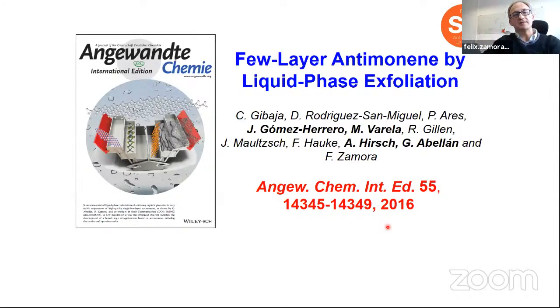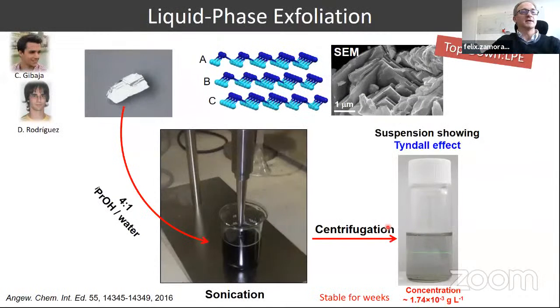And then we decided to extend the possibilities to isolate this material, and we tried to do this isolation by using liquid phase exfoliation. Here we start with the same crystals, beta antimony. As I told you before, you have to look for solvents able to somehow assist the exfoliation of this structure, and then you need to incorporate energy to the experiment in order to assist the final delamination of the material. Checking a lot of possibilities, we ended up with this mixture of solvents as the most suitable one for delamination, isopropanol water 4:1, and then we end up with this suspension.